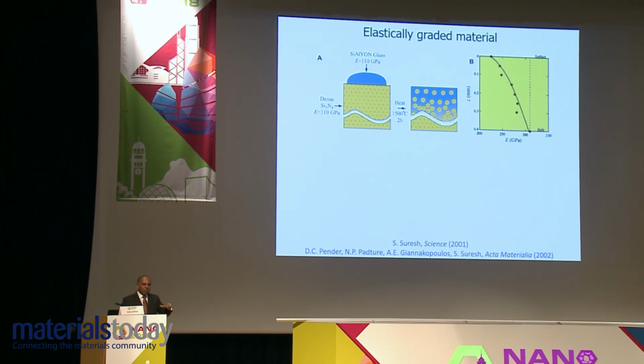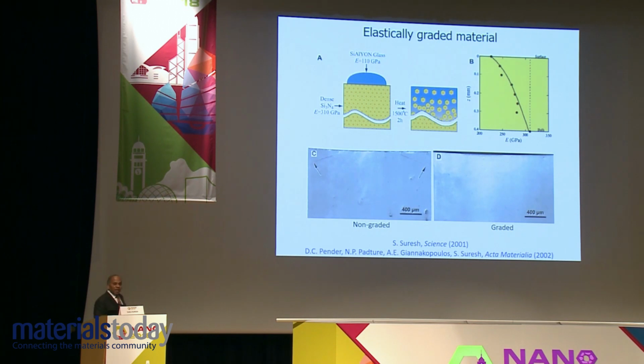But now if you do the experiment in a graded material, you completely suppress the fatigue crack during normal indentation in this elastically graded material, which has no plasticity. So that was a very clear demonstration. So here is the picture. On the left-hand side, if you take pure silicon nitride and you have no gradient, you get a classic Hertzian cone crack. But if you grade the material, the one that I've shown at the top figure, and you do the same indentation, you completely suppress this. This is macro indentation. So we showed this in aluminum oxide, silicon nitride, several other ceramics.